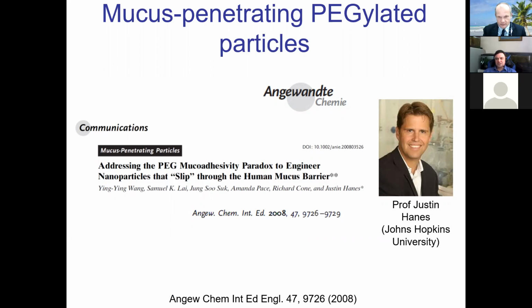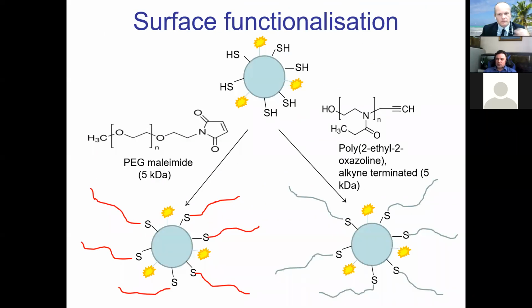And Professor Hanes demonstrated that there's a huge benefit from making the particles more penetrative. In fact, there's still an argument about whether you need to have a mucoadhesive system or mucus-penetrating. So PEGylation was reported, but then I decided to contribute to this field by introducing our systems. So we took a model of thiolated silica particles.